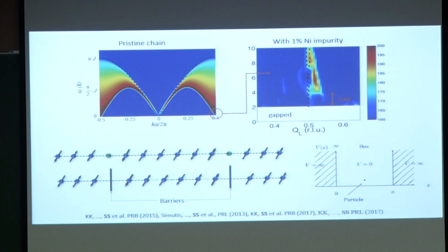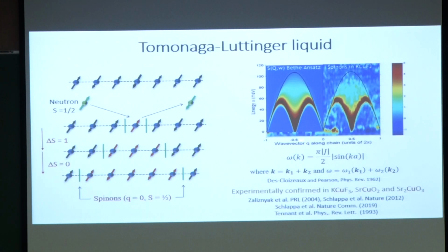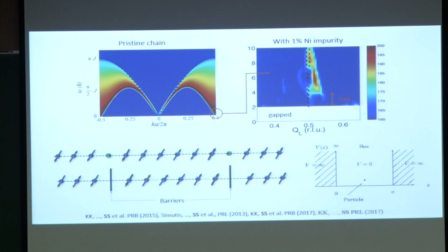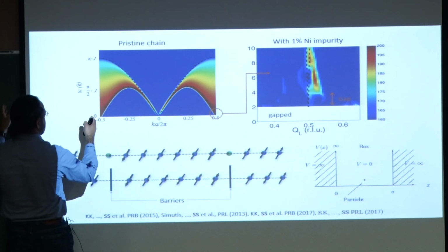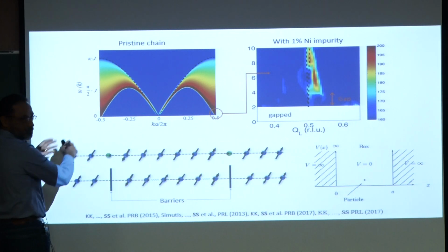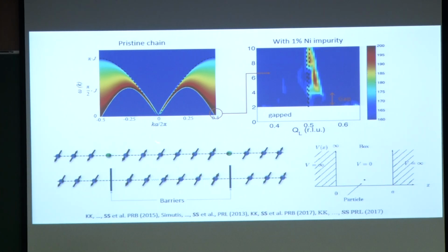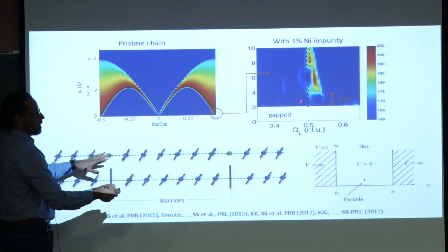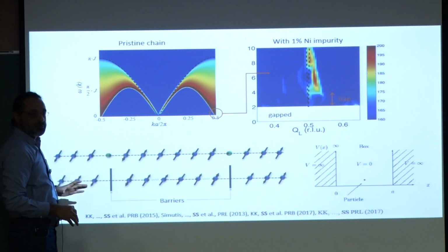For a pristine chain, I showed you in the previous slide how the calculated excitation spectrum would look, and I am showing it again in the next slide, but only one half of it, in a different region, from minus 0.5 to plus 0.5. What I mean is that if you take this and paste it here, then you would see the two-spinon continuum. So this is actually the experimental result, and in this last slide I'm trying to explain to you what is going on.